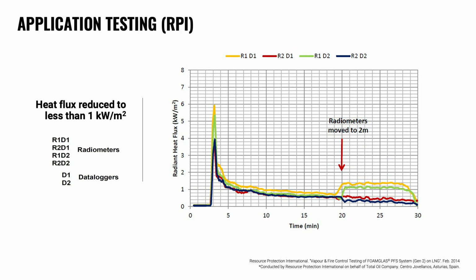This is an expected phenomenon to see at the beginning of a test like this. The LNG was introduced to the pit several minutes before it was ignited. This spike in heat flux is a combination of the burning of previously vaporized LNG as well as the vaporization and burning of residual LNG resting on the modules and sidewalls of the containment pit. Once these initial vapors were allowed to burn off, the measured heat flux reached a steady state, evidence of the reduced vaporization and burn rate that's taking place.